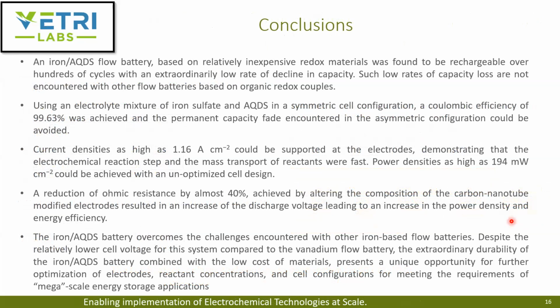So the conclusion is that they used an inexpensive Iron-AQDS flow battery and found it to be rechargeable over hundreds of cycles with a very low rate of decline in the capacity. They can also obtain a Coulombic efficiency of 99.63%. And they can obtain a current density as high as 1.16 amp per centimeter square and a power density as high as 194 milliwatt per centimeter square with an un-optimized cell design.